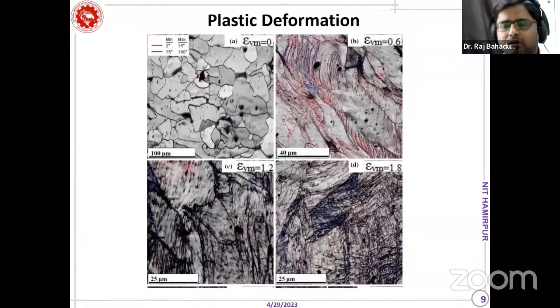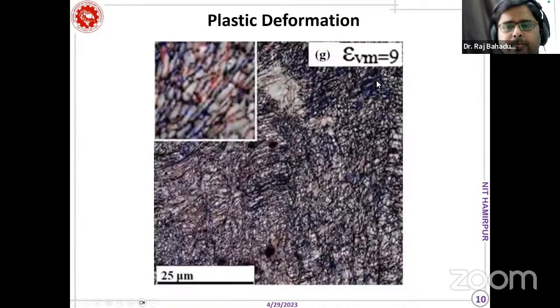So let me do this here. Okay, so this is the micrograph of the low carbon steel. Before deformation, you can see the coarser grains, and after deformation, you can see the subgrains start forming, or deformation bands start forming within the grain. If we keep on increasing the level of strain, or keep on deforming the same material, then you can see the refinement of the microstructure. You can see here the very fine grains, and this is the accommodation of almost 9 equivalent strain on the material.